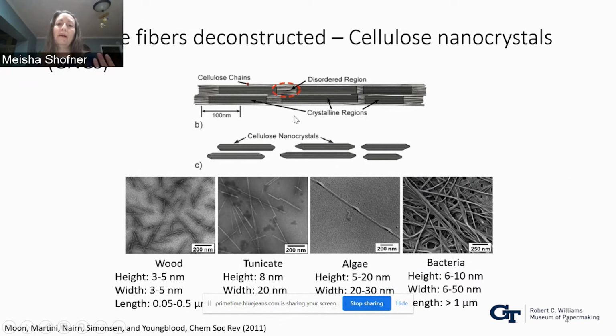So if we're thinking about a material that we would like to incorporate into something like a composite or other structural material, having these areas of very nicely aligned molecules should lead to nice structural properties. If we want to get them out of the microfibers, then often they'll be treated with an acid, many times sulfuric acid, and that sulfuric acid will preferentially destroy these disordered regions, leaving behind these ordered molecules, which are like little needles made of wood.